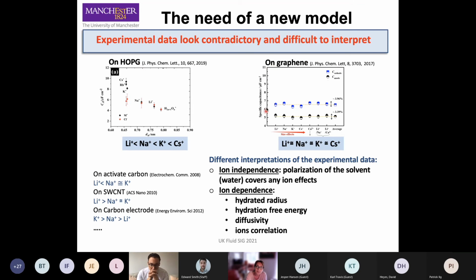And these experiments, again, this is the specific capacitance measured on, I think it was a bilayer of graphene actually. So you can see that here what it looks like is that the value of the specific capacitance depends on the ion. So there is an ion-specific behavior. So some ions are more adsorbed than others, but exactly the same experiments seem to show instead the opposite, that there is no ion specificity.